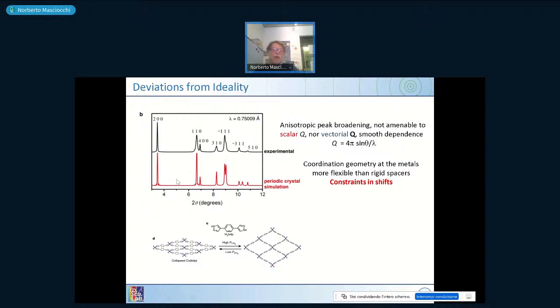You can see that the periodic crystal simulation gives the correct position. The intensities, the integrated intensity are somewhat correct, but the width of a peak is different. So the integrated intensity of 110 and the one down here match. So the area under this peak and under this peak are correct, but this peak is broadened while the 400 is not. The 111 is very broadened.